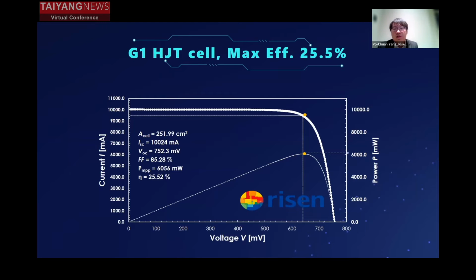So Risen got the highest 25.5% cell efficiency with a 120 micrometer wafer and double side microcrystal silicon double layer in 2021 Q4. And this is a low wafer thickness, which means roughly only 100 micrometer wafer after the texturing process.